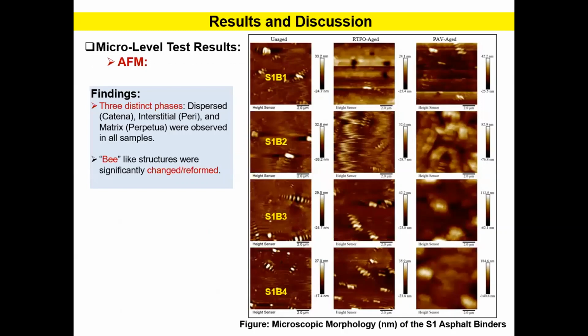The micro level AFM test result shows that in all unaged asphalt binders, we found 3 distinct phases, which are called dispersed or catena phase, interstitial or peri phase, and matrix or perpetua phase. However, these phases were significantly changed, disappeared or reformed in case of short-term and long-term aging. Here you can see in the picture a typical AFM-based map of an S1 asphalt binder. Also, the bee-like structures were significantly changed or reformed due to the aging of the asphalt binders.